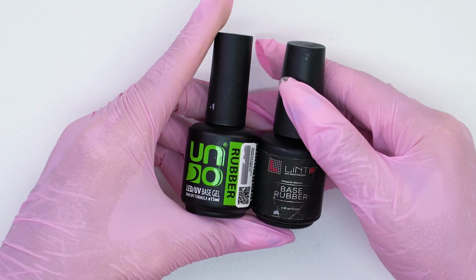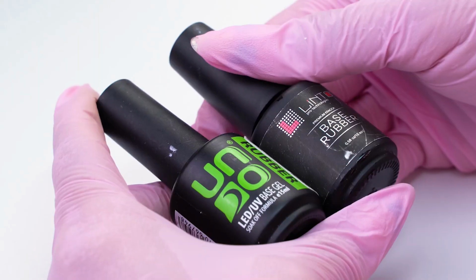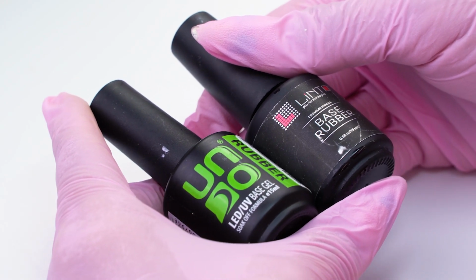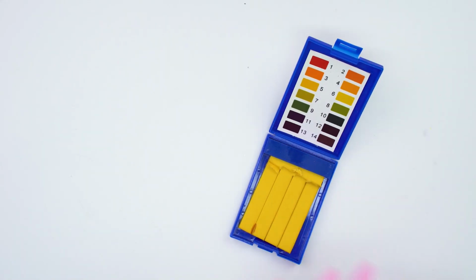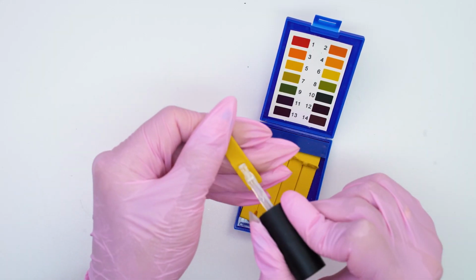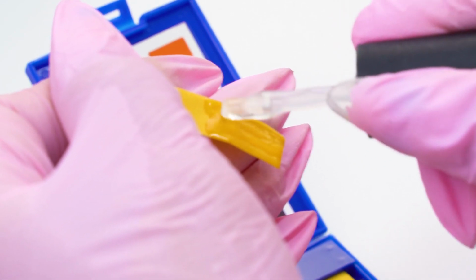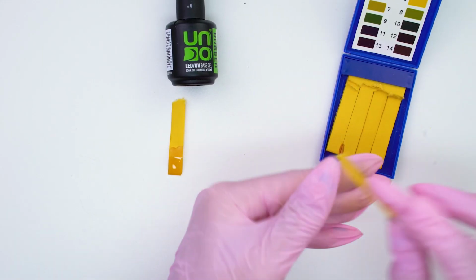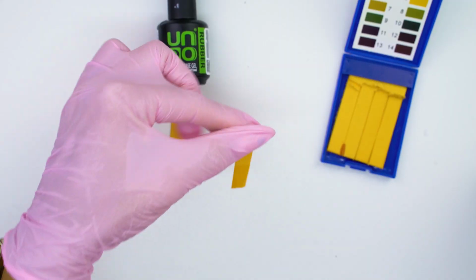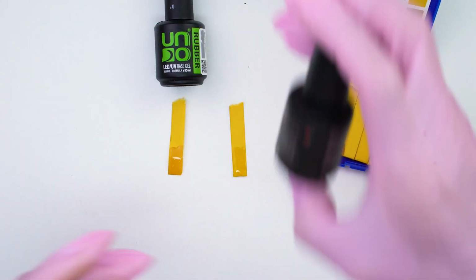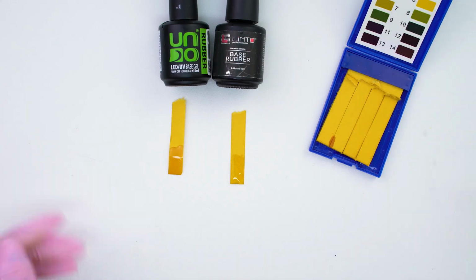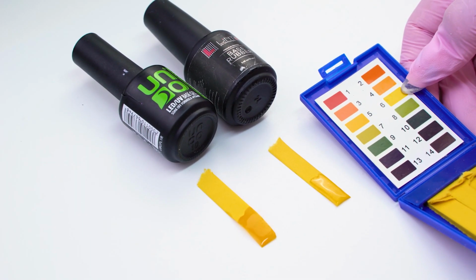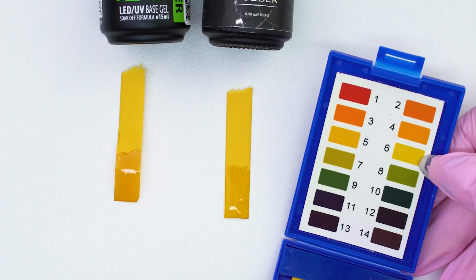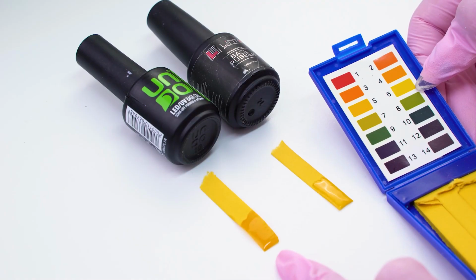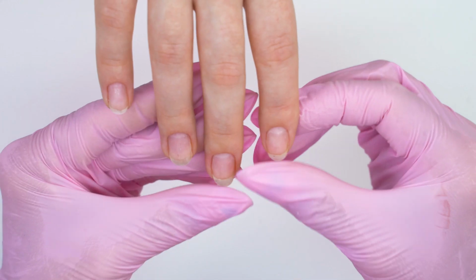We should also pay attention to the base coat acidity. Acidic ones have better adhesion, but when we apply them in a thick layer on thin nails, such base coats may cause a nail plate burn. Acid-free ones may not hold on perfectly even if we use them with a primer. We can form the underlay with an acidic base coat and then align it with a low acidity one. In this case, there won't be too much acid on the nail surface, and it won't get burned.